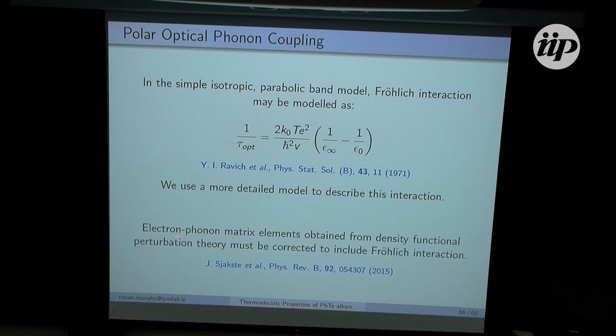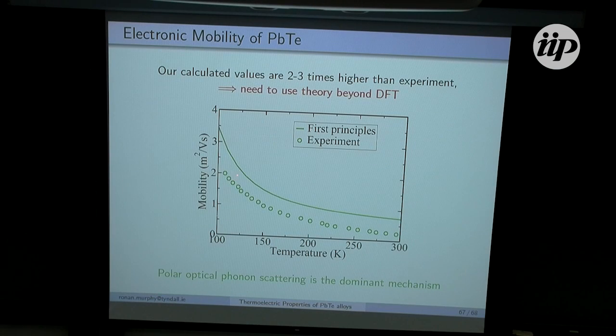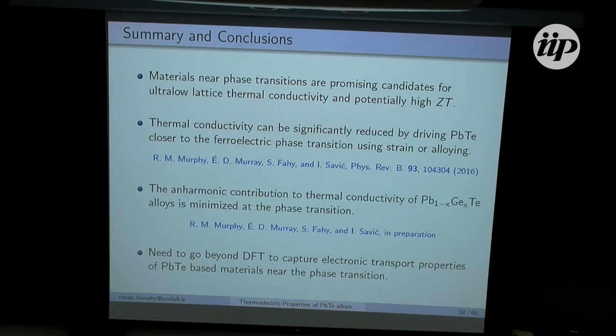You might also think that you could calculate this from electron-phonon matrix elements, but previously these were captured inaccurately by density functional perturbation theory. Just to mention, this group here has worked on improving the accuracy of these electron-phonon matrix elements to capture the Fröhlich interaction properly, but I won't dwell too much on that. I'll move on and show our mobility for lead telluride. Again, we get a value about 2 to 3 times higher than the experiment. So far, from what we can tell, polar optical phonon scattering is the dominant mechanism. But it is clear we need to move beyond DFT to properly capture these electronic properties.